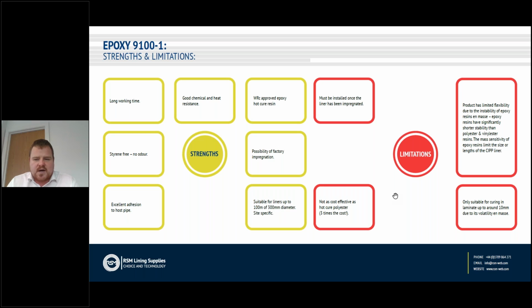We can give you advice on the cure of thicker epoxy liners should you have those specifications, but it's incredibly important to do that so that we get the absolute maximum from the cured composite. We can also consider to add glass to the liner to ensure we meet the design characteristics whilst not increasing the thickness too greatly.